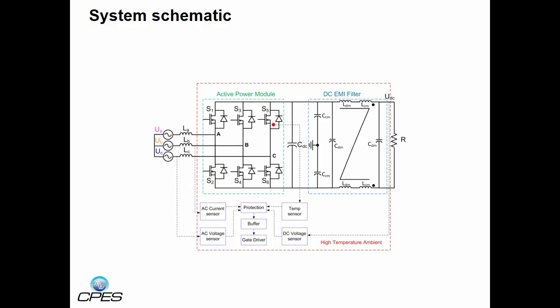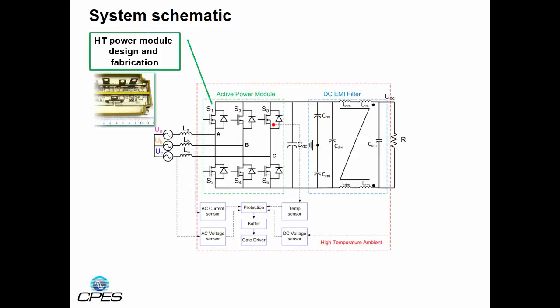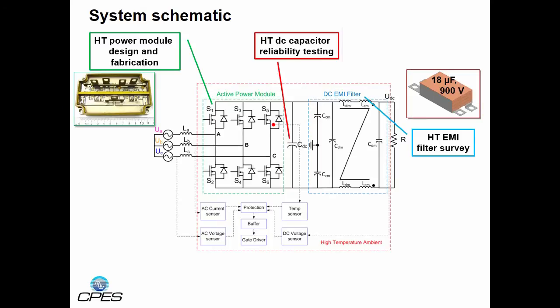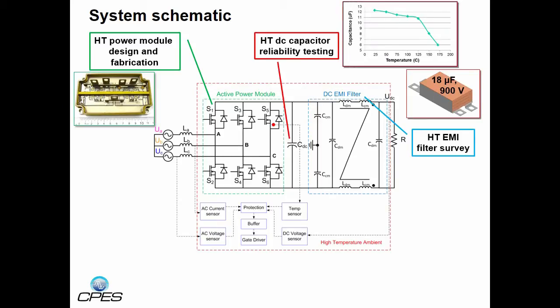This is a schematic of the 50 kilowatt converter, where the components inside the dashed red box are to be operated in the high-temperature environment. As was mentioned earlier, custom high-temperature silicon carbide power modules were fabricated in the CPES packaging lab due to the lack of commercially available high-temperature modules at the start of this project. An extensive survey was conducted on high-temperature magnetics in order to realize a high-temperature EMI filter. A survey on high-temperature capacitors was also performed.